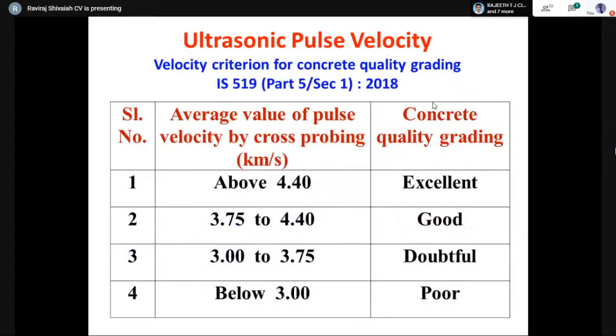Now, some standard values that we are talking about as per IS 516 Part 5 Section 1, 2018. This code has been brought out very recently, some 2 years back. The earlier code was from 1992. Two years back, this code has been revised. And as per this particular code, any pulse velocity that you get which is more than 4.4 km/s, the concrete grading quality is excellent.